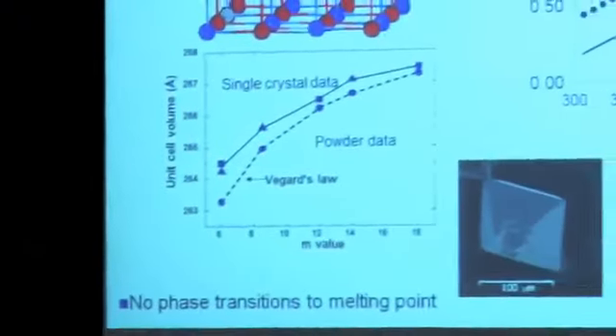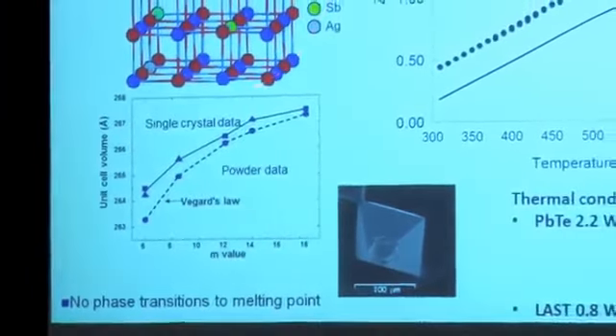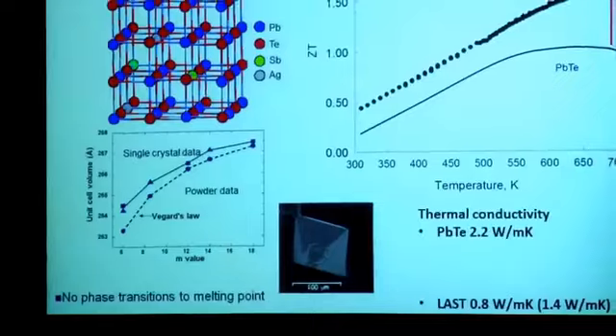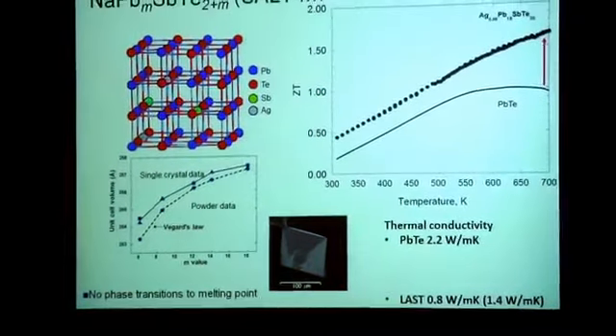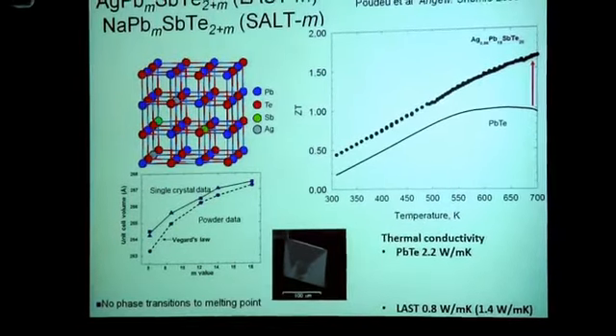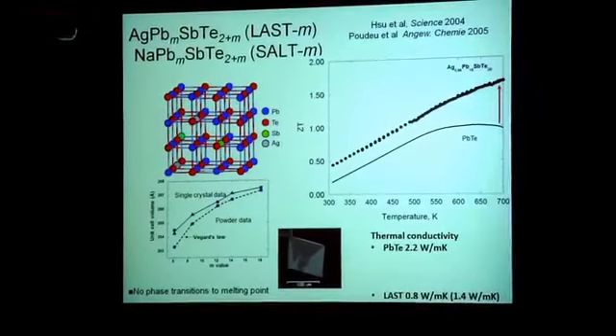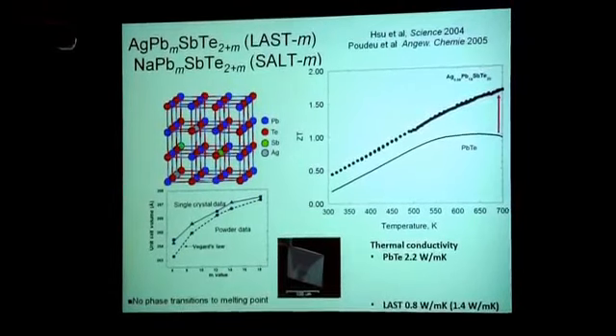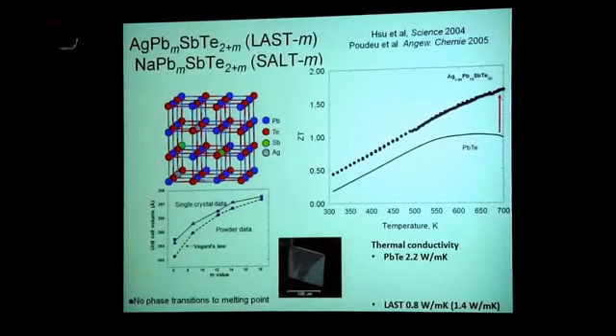So some time ago, we were playing with this system because we thought we would take the lead telluride structure, which is cubic already, and take lead atoms out and replace them with silver and antimony atoms. A lead atom is 2+. You take 2 lead atoms, that's 4+, and you put 1 silver, which is 1+, and 1 antimony, 3+, so your average is 4. So you can make this series of compounds, which we call LAST, lead, antimony, silver, tellurium, with any M you want.